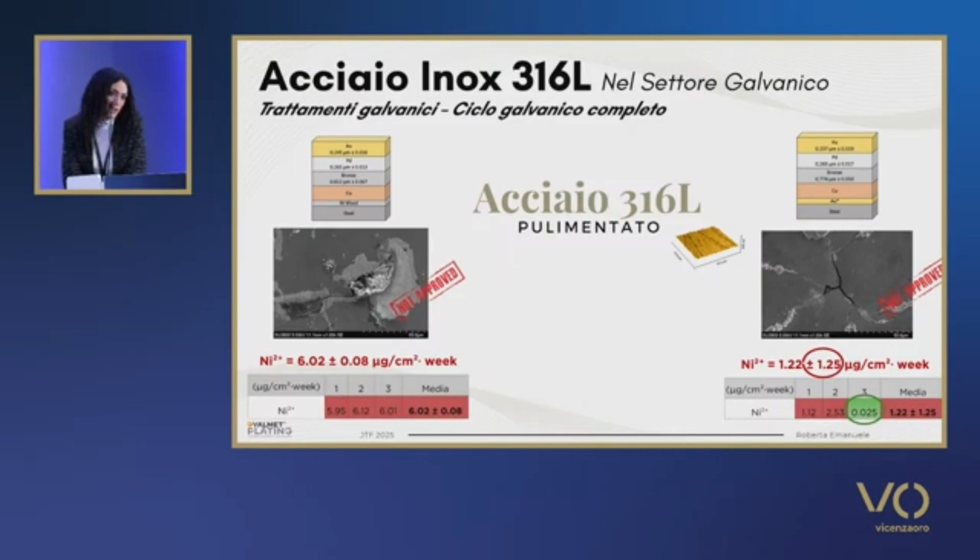And this increased the standard deviation, coming very close to the average value. Based on this study, we may say that our assumption that there was a nickel dispersion in the intermetallic phase was wrong, because the time since the preparation of the sample and after the week of release is not enough to enable nickel to get across the galvanic coating.